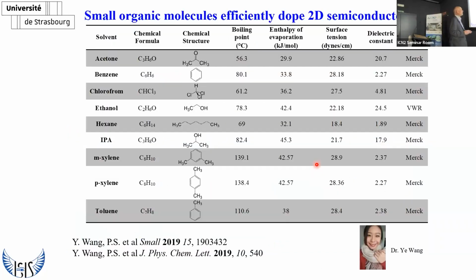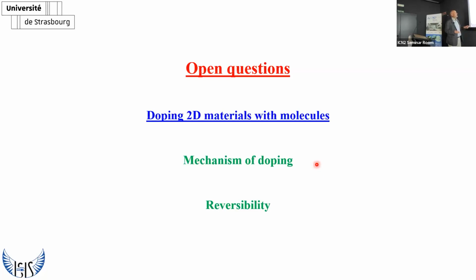Now, first of all, I'd like to stress that you should watch out about any kind of solvent you might use, because it's not innocent. These are a number of molecules that you might think to be innocent, to be used to wash the surface of 2D materials and not to dope the 2D materials. And these two papers that Ye Wang and our group have published show that actually all these molecules act as dopant, okay? So the take-home message of this paper is if you can deposit molecules by vapor deposition, that is always much better. So avoid the use of any solvent, because even the most simple ones are doping to a certain extent. Now, in fact, let's talk about doping.